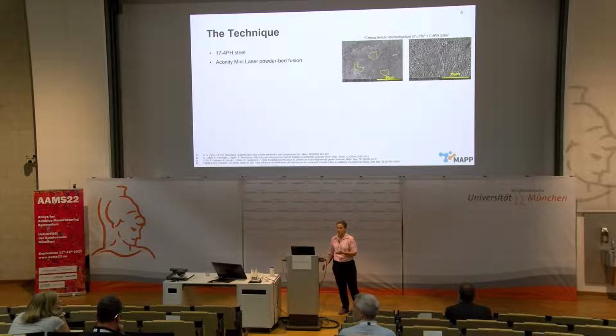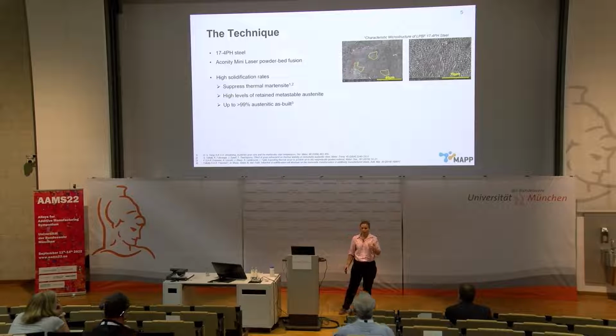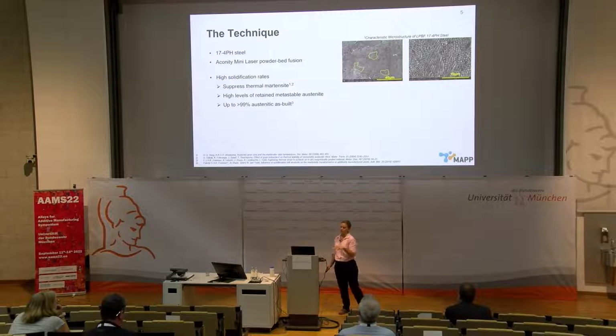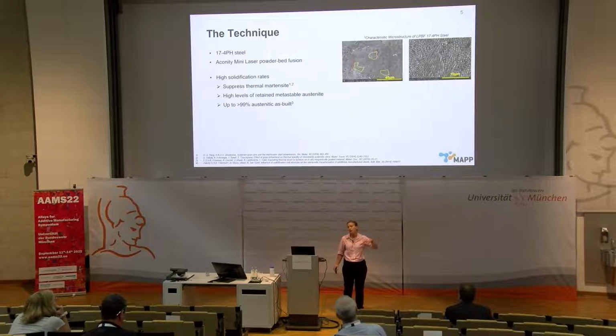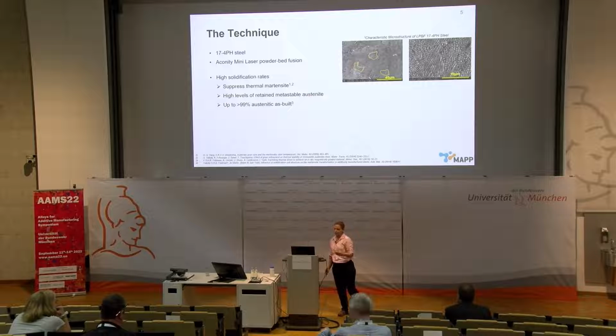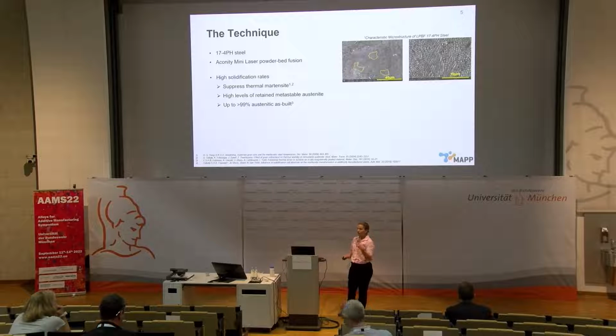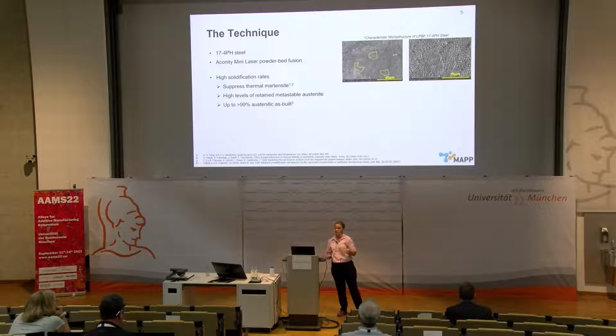local cooling rates. But what we find is those high solidification rates actually suppress thermal martensite. So we're suppressing that martensite start temperature, and that's something that's been known about in the literature for a long time. So there's two references there. One was from Harry Bhadeshia, talking about the effect of austenite grain size on the martensite start temperature. And when we suppress thermal martensite, what does that give us? Well, it gives us high levels of retained metastable austenite. And in some of the work we've done, we've seen up to, or in excess of, just about 99% austenite as built. So this is something that you just can't get conventionally.